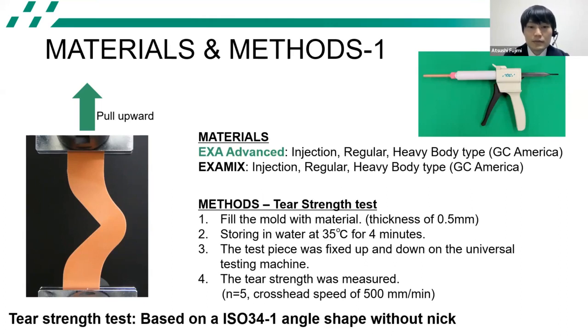Methods: first, fill the mold with the material, thickness of 0.5 millimeters. Second, store in water at 35 degrees Celsius for 4 minutes. Third, the test piece was fixed up and down on the universal testing machine. Finally, the tear strength was measured. Sample size is 5 and crosshead speed is 500 millimeters per minute.